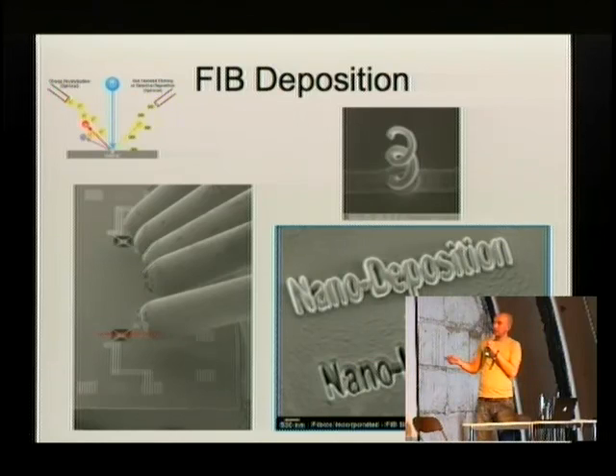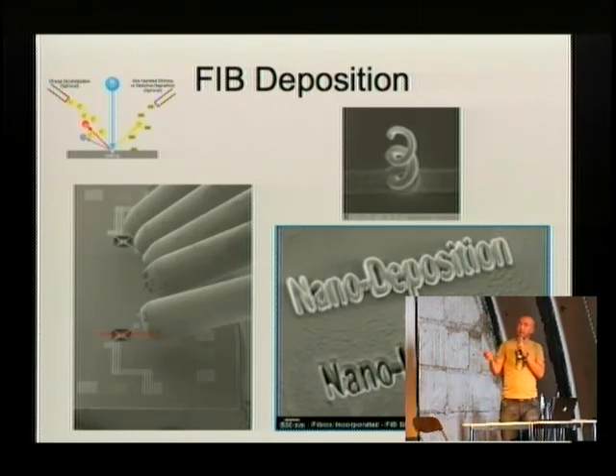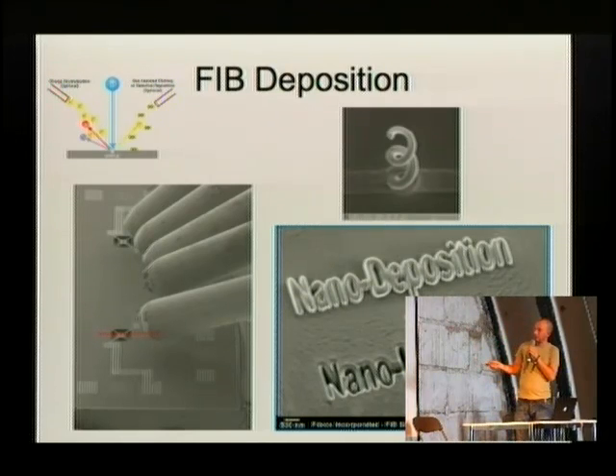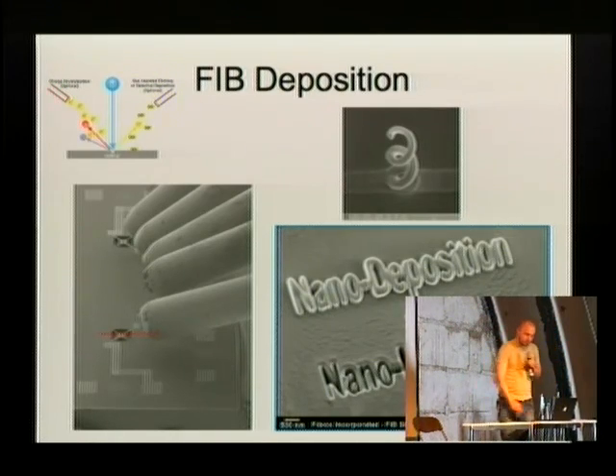material. Here you see in the image some chips on a silicon substrate, and here you see 5 small needles that come in, through which the gas that is used for this decomposition is pumped. With that you can also write very small structures. Here we see an example where on the one side you have the substrate milled away, and on the upper side there was some insulator deposited onto the substrate by this technique. And if you do it carefully, you can even create 3-dimensional shapes.